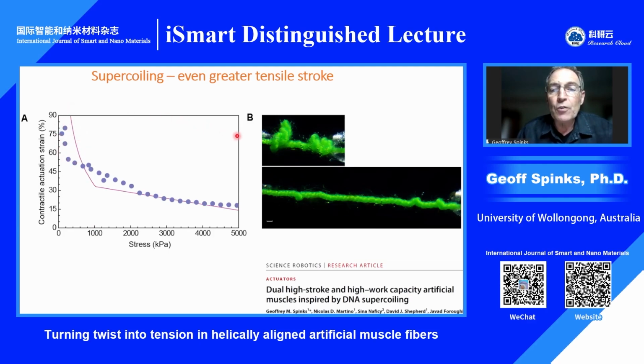And the images on the right show what's happening. We start with a twisted fiber, but the process of volume expansion actually causes a supercoiling phenomenon, which ends up looking like these sort of knots here, or at higher tensions, just little kinks in the fiber. So as the fiber bends out of plane, its end-to-end length decreases, and that's what's producing the really high strokes in these artificial muscles.